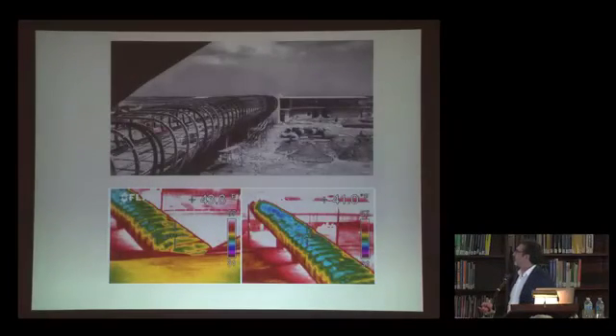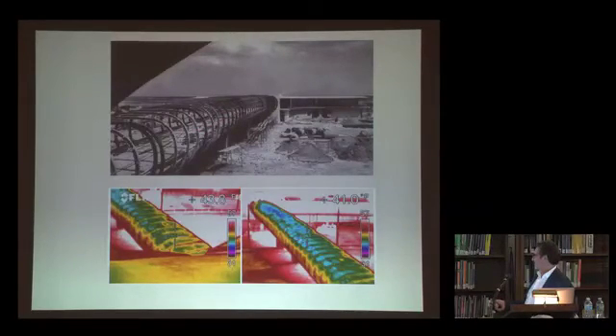So for us, our initial job was to quickly try to find locations underneath the existing coatings that might show signs of distress and damage, as there was no way that we were going to be able to remove the coating in the design phase. So we worked with an engineering firm who specializes in non-destructive evaluation, Atkinson Nolan, who, using microwave radar and infrared thermography, helped us try to find some hot spots through the coatings. So I just want to show you, here's one of the tubes being constructed, and here's one of Atkinson Nolan's thermographic images. Quite amazing what it can show in terms of, if you're lucky, what the actual substrate materials are and what their layout is.